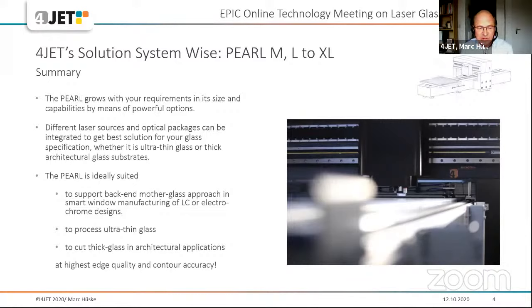Pearl is actually ideally suited to support the backend mother glass approach in smart window manufacturing. Smart windows are those switchable windows where you can apply a voltage to the glass and you get a changing of the transparency state going from light to dark and vice versa. And those windows can be cut, also in the mother glass approach, meaning you get a very large piece of glass which you have to cut into small products. It can also be used to process ultra thin glass going down to 30 microns and cut thick glass applications in architectural windows. And as I said, it's the perfect edge that you receive with a very low surface roughness to get a high edge strength and a very accurate contour.